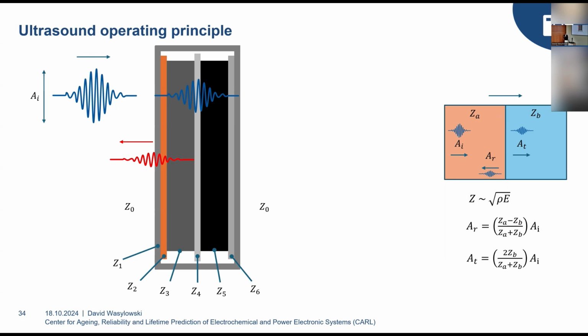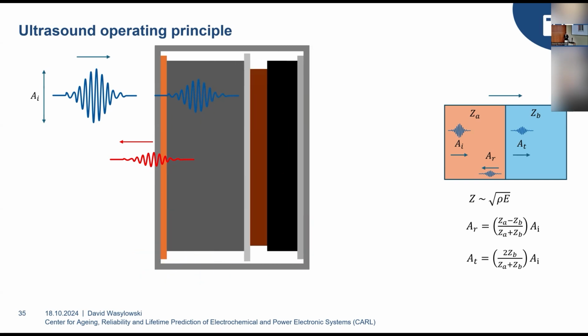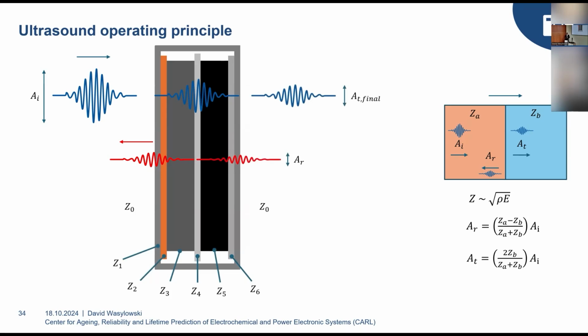And if we for now assume that all of the acoustic impedances within the battery are pretty similar, because there's this porous material and we just drench it in electrolytes, so everything is fairly homogenized within the battery, we don't get any major reflections within the cell. The next major reflection will occur when we try to exit this battery on the other side. So again, we have this very large mismatch between the solid material from the cell housing and this liquid electrolyte. So we end up with this transmitted ultrasound wave here, which is obviously lower than the incoming ultrasound wave.